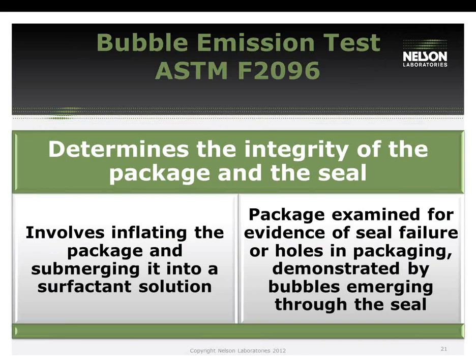The next option is a whole package test. It is the bubble emission. The way that it works is you inflate the package under a surfactant fluid, and you're looking for holes in a continuous stream. It's a very easy test. You have to be very careful because you don't want to put the pressure in the package to the point where you'll pass what's called a bubble point, and it looks like you're generating bubbles from all over the package. It looks like it fails. So making sure that you have the correct pressure for the inside of the package is a key to the test.